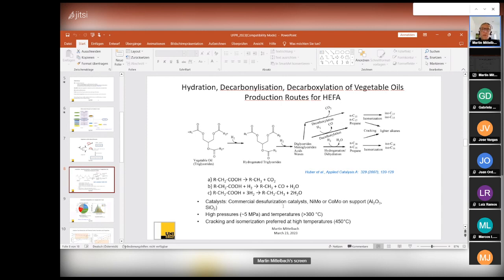It could be some commercial desulfurization catalysts based on nickel or molybdenum on different supports. The reaction conditions are high pressures, around 5 megapascal, and temperatures over 300 degrees. If you go to higher temperatures, you have a lot of cracking, and isomerization is preferred at high temperatures.